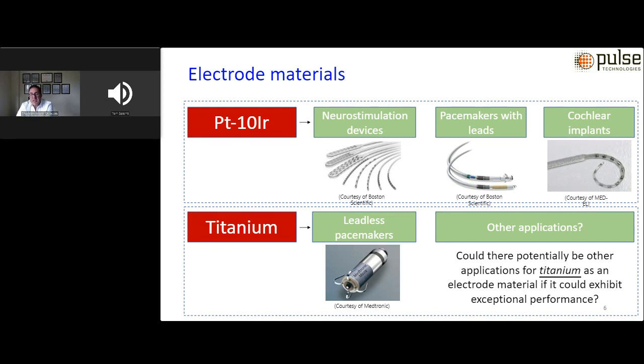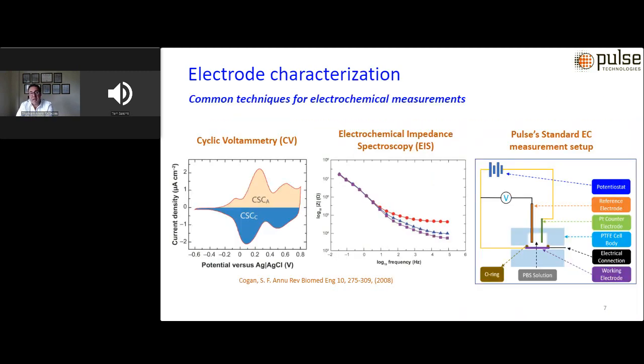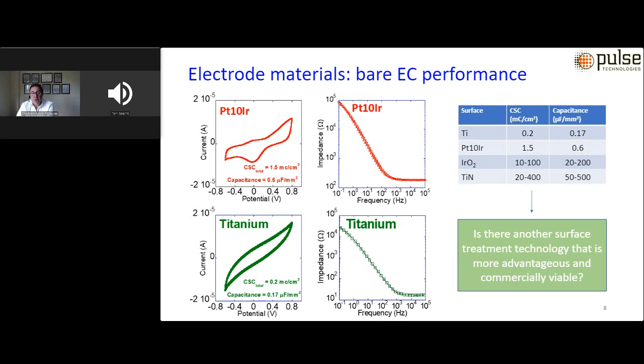So we use essentially CV and EIS measurements in a 3-electrode cell comprising a silver chloride reference electrode, a platinum counter electrode, using commercially available phosphate buffered saline or PBS solution. And going forward, basically the results that I will show talk about these two measurements and the comparison of electrodes using these two measurements.